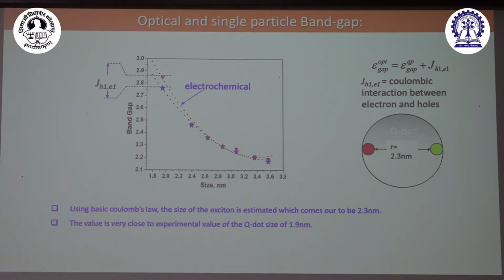So that energy difference is nothing but equal to the Coulombic interaction. And once I know the Coulombic interaction, I can estimate the size of the exciton. Agree? Because the size of the exciton is equal to the Bohr radius at that point. So I can now estimate, using a simple difference, the size of the quantum dot. That's what we did here. And by using our method, the size of the quantum dots came out to be about 2.3 nanometer. So it is very close to the TEM images we recorded for this particular size, and what is estimated from this, both numbers match very well. So the Brus theory we applied works for our system.